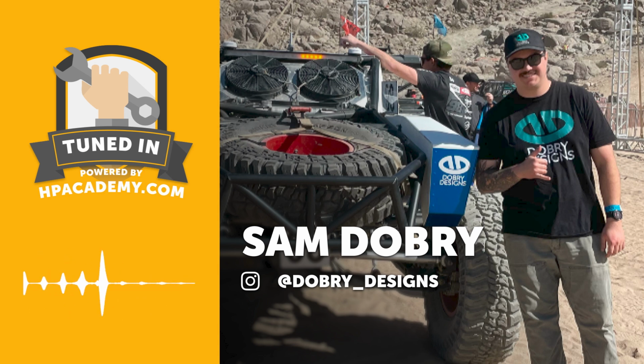And you'll see that fairly common across all endurance motorsports: when they run thicker oil, they'll go down this pretty traditional loop of, oh, thicker oil. Oh, well, now I have heating issues and my parts are still failing. And I have a different part failing now because it's hotter. And then they put a cooler on it. And now you're trying to pump thick oil through a cooler. Now your pumps start to fail. And now you have all these different recipes of new failures, when it's really just your oil from the beginning.